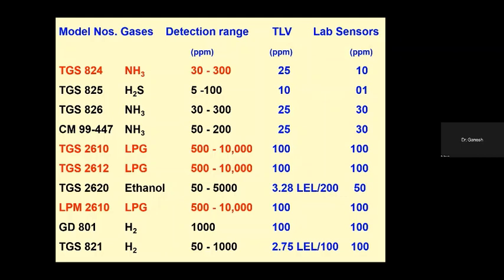LPM 2610. So here TGS 824 is the ammonia sensor. Its detection limit is from 30 ppm to 300 ppm. It means that if the ammonia gas is leaked in the environment above 30 ppm, then this TGS-824 sensor gets operated and it gives the signal. However, 25 ppm is the threshold limit value of the ammonia gas, and if a 25 ppm leak is detected, then we can avoid the hazardous effects. But here TGS-824 has the limitation of 30 ppm.